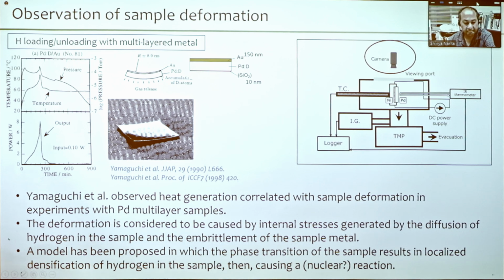So a model has been proposed in which the phase transition of the sample results in localized densification of the hydrogen in the sample, and then causes the reaction. I don't know whether it is nuclear or not, but some reaction. So that's the reason why we put the camera in, to observe the sample behavior and sample deformation during the desorption experiment.